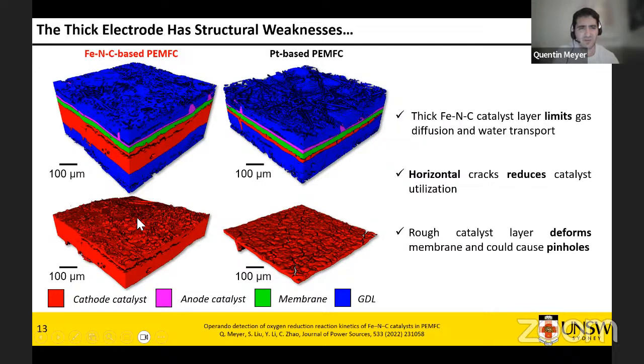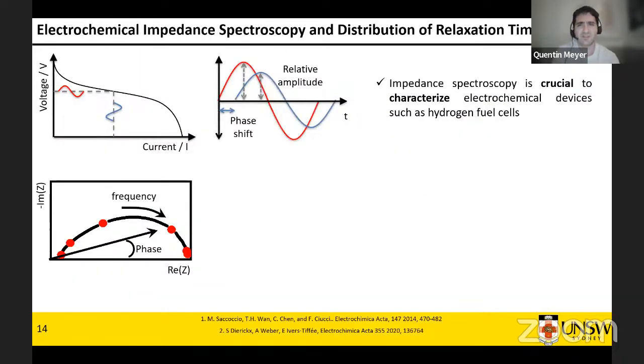And this may be so rough that if you try to use commercial membranes from companies like Gore or other suppliers that are very, very thin, probably less than 10 microns, you may even create pinholes, because you're pressing something very rough on something very, very smooth. That's something to consider. So now this is a physical approach to it. Now we want to do some electrochemical measurements.